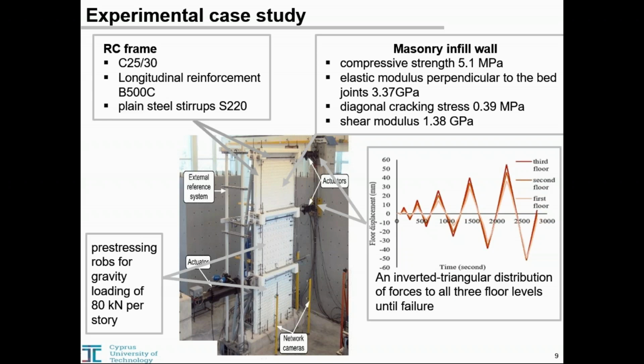Pre-stressing rods were used on the foundation beam of the specimen to provide full clamping of the specimen to the laboratory floor. The gravity load was equal to 80 kilonewton per story, in order to represent the fraction of the permanent load acting together with the lateral loading. Three actuators were mounted on the specimen, one per story, to impose the cycles of loading. A total of 5 cycles of loading were finally applied to the masonry-infilled RC frame, and an inverted triangular distribution of forces at all 3 floor levels was kept until failure occurred.